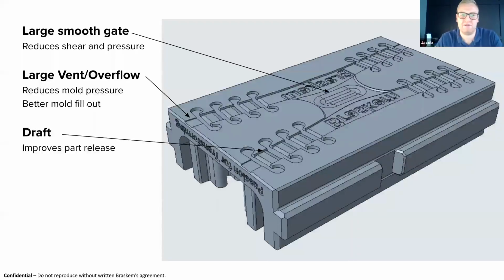The more draft you can add, the better. If your surface allows it, if your engineering tolerances allow it, add draft. It's going to help with mold release. Typically, I think in metal molds, you're talking very low percentages, maybe 1%. In our case, we're talking up to 4 or 5% if you can allow for it.